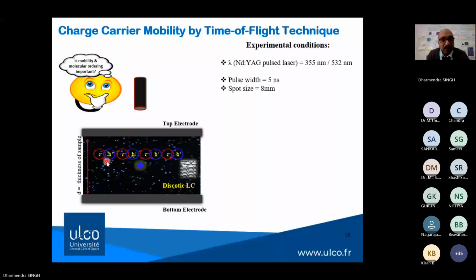So these excitons will dissociate into electron and hole, and due to thermal agitation they will be collected at the top electrode, because this light was absorbed within the 10% of the thickness of the device. And what happens when you apply a positive or negative bias at the top electrode? Then Coulombic forces will be effective here. For example, if we apply a positive bias at the top electrode, then due to Coulombic repulsion, this bias will repel holes, and these holes will propagate towards the bottom electrode by interacting with these materials. And when you apply the negative bias, then only the negative element, the electron, will propagate towards the bottom electrode.